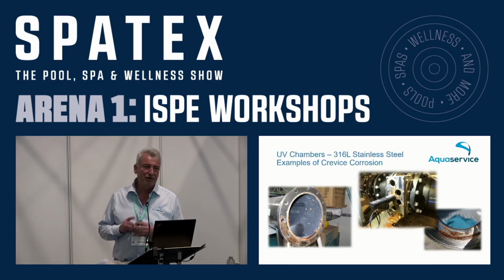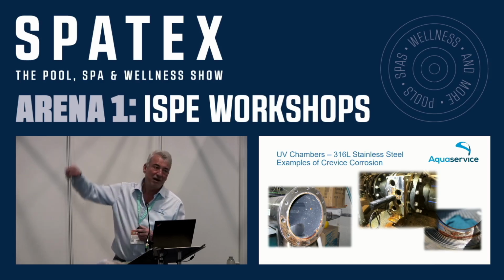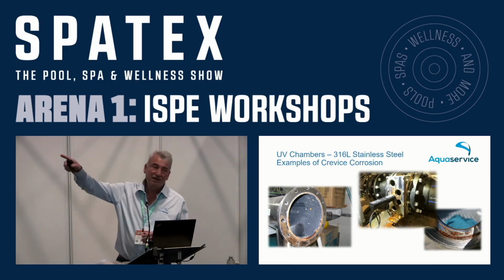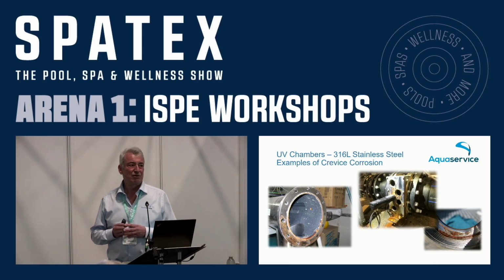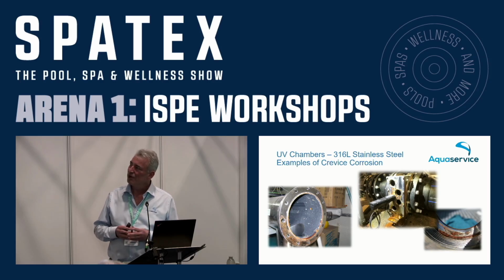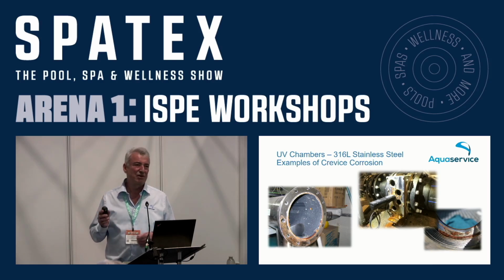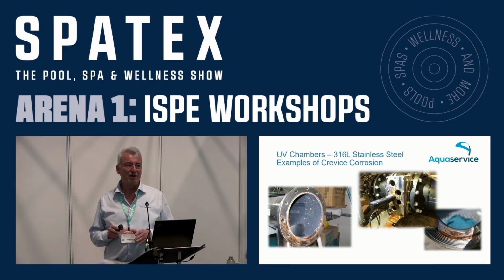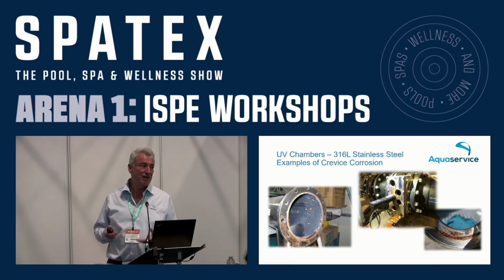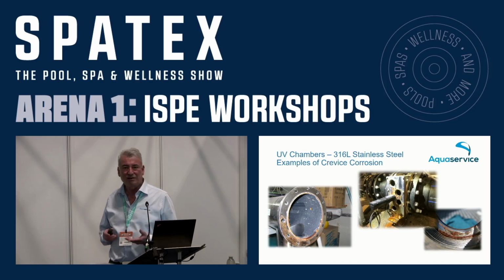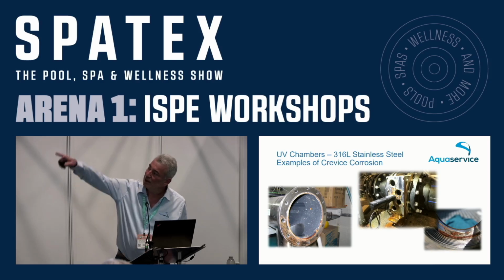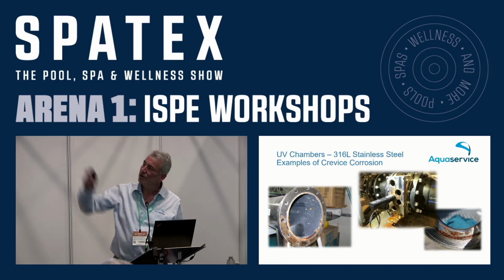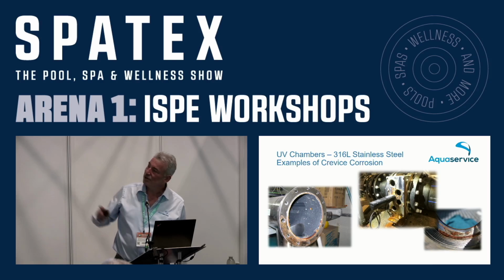So these are examples of crevice corrosion on UV chambers. On the far left, you see the end plates removed from a UV chamber, and that corrosion around the rim is crevice corrosion. Here in the center, that's a UV chamber that is installed still on an aquaculture application. So the water is seawater. That's where the chloride comes from. But in this case, the setup allowed the UV to run at full power when there was virtually no water flow. So the UV lamps heated up the water to a degree where the chloride attacked within the crevices. So you see leakage of ferric oxide coming out of where the lamps would be connected into the chamber.